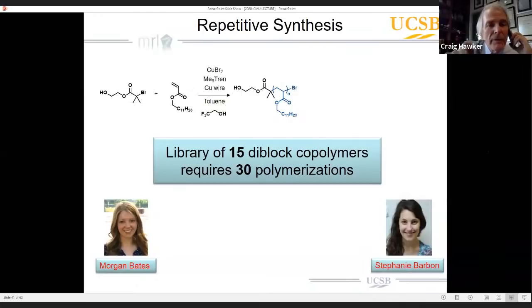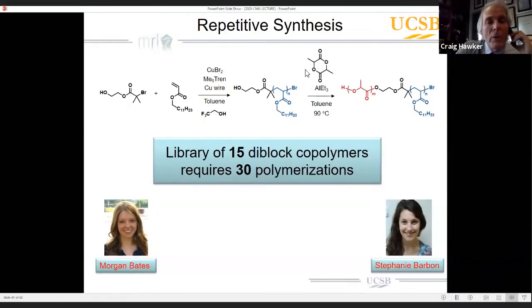So Morgan, together with Stephanie Barbon, a postdoc in the group who's now at Dow, did what everyone traditionally did, and that's make a library of different block copolymers using classic controlled radical polymerization. You'll see the trifluoroethanol, which is this privileged solvent that Athena introduced to the group, works really well for the polymerization of acrylates. It's a fairly simple thing to make multiple starting acrylate blocks, and then use controlled ring opening polymerization to open lactide to give polylactide, polydodecyl acrylate diblock copolymers.